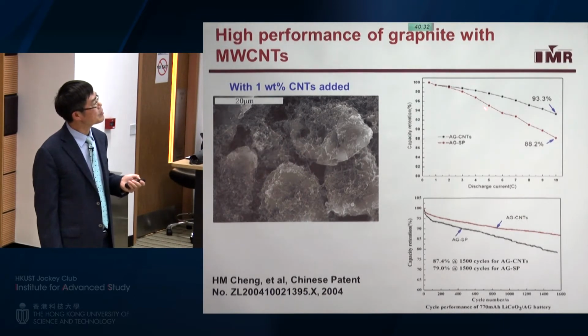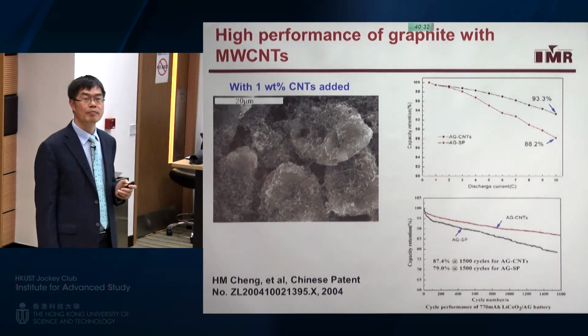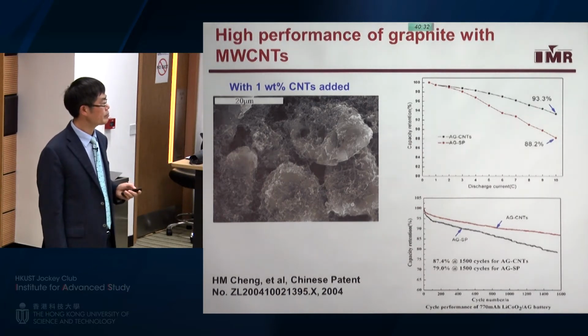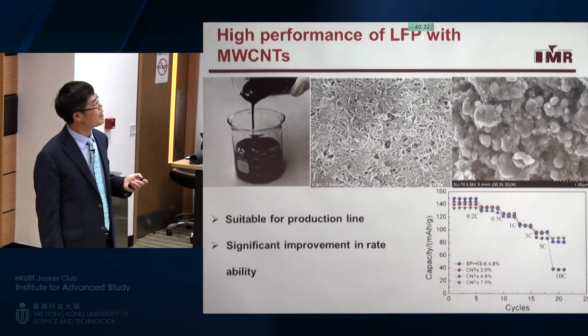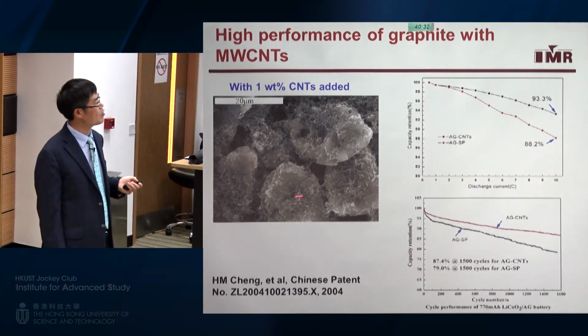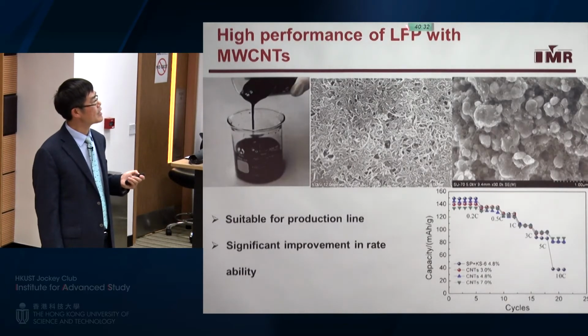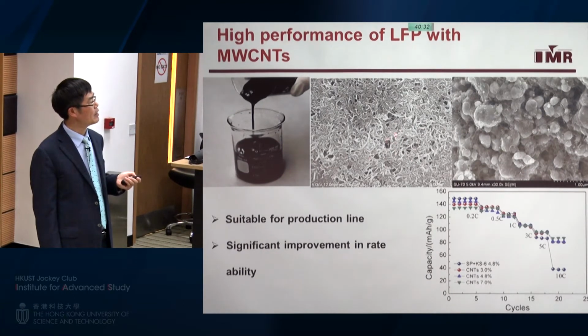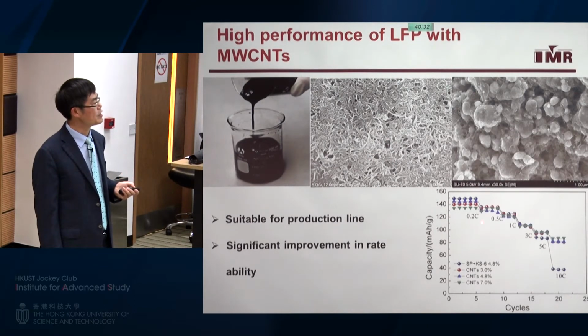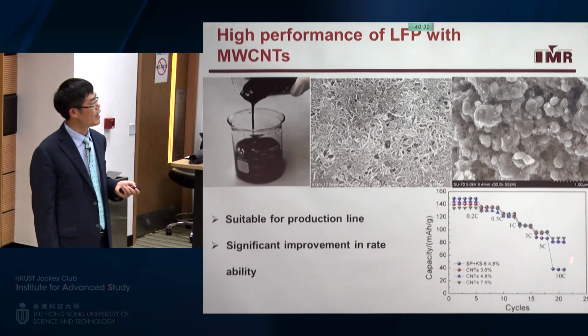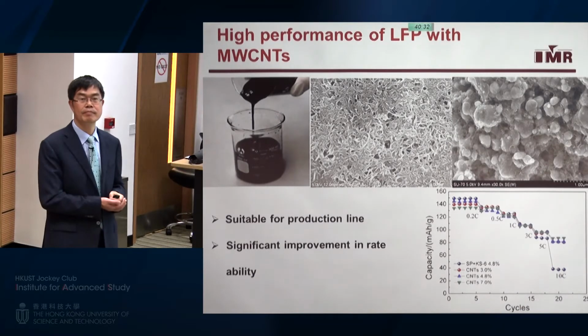As I show you, with carbon nanotubes the cyclability has been greatly improved for many types of electrode materials. Here is lithium iron phosphate, and this one I think is a graphite anode material, and this is a cathode material. We can make this carbon nanotube slurry and then make a network which is very well conducting. You can see here, in particular at a very high rate, the capacity is still very high compared to the carbon black conducting additive.